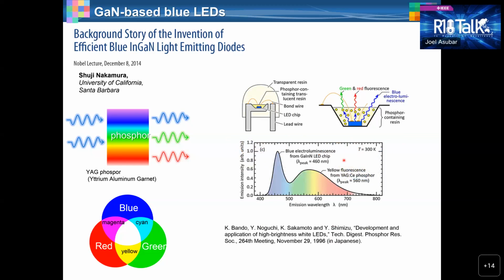This is a spectrum of blue LED and phosphor combination. This peak is the blue electroluminescence from the blue LED, while this peak is the yellow fluorescence from the cerium-doped yttrium aluminum garnet phosphor, which is actually a broadband emission of green to red and appears yellow to the human eye. Here we can recognize and appreciate the importance of blue LED, because out of just blue light and a phosphor, we can actually generate white light. And therefore, the 2014 Nobel Prize in Physics is very much well-deserved.